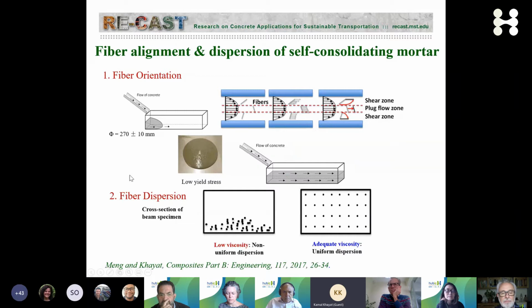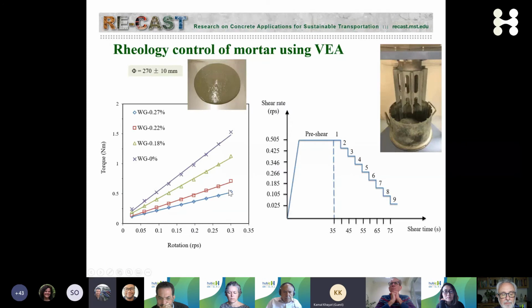So we've been working on adapting the rheology of the suspending mortar to enable the concrete, as it flows, to orient the fibers in the direction of the flow. But when the flow stops, this very highly flowable concrete adapts the viscosity and the thixotropy to be able to suspend the fibers. So we've been working on different procedures, and each of these lectures can be elaborated later on in our discussions in the coming year, if you have interest. But here I'm just giving you a small teaser, if you would, about some of these technologies.